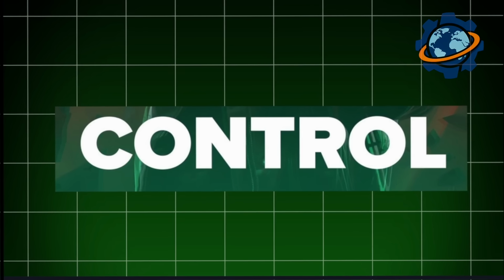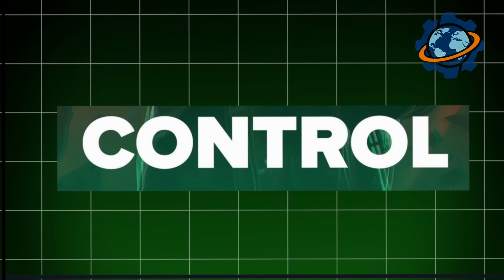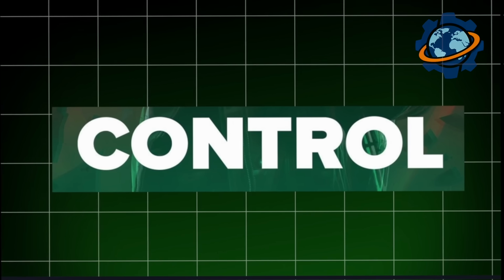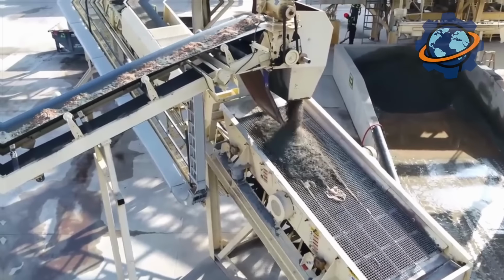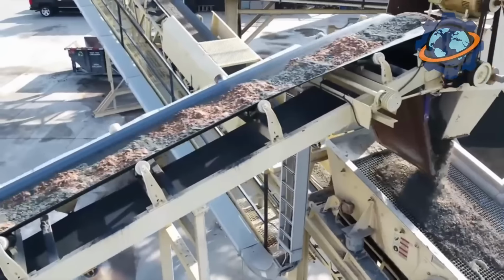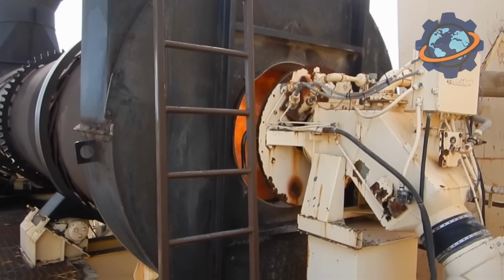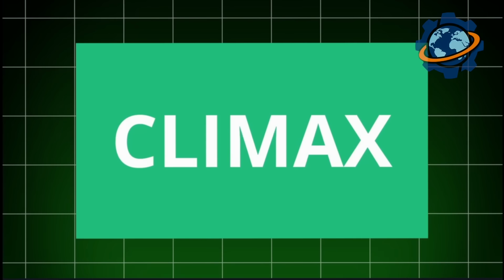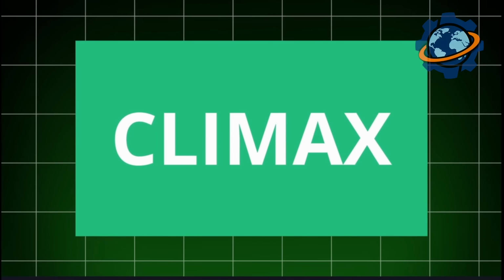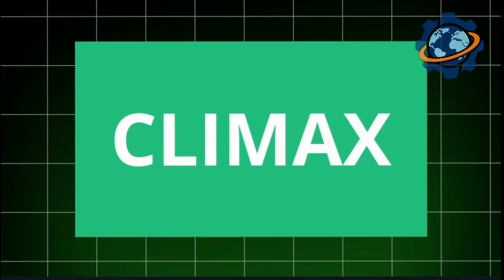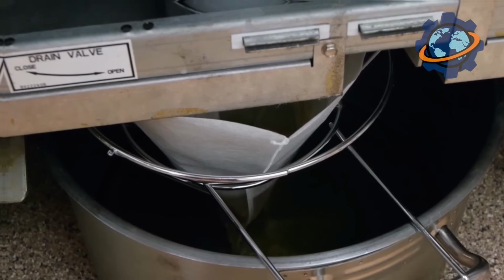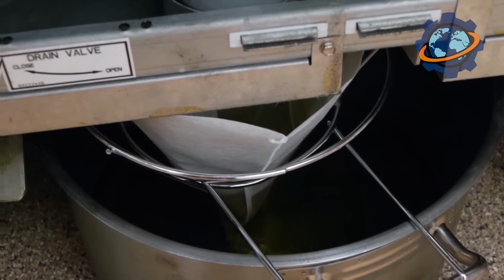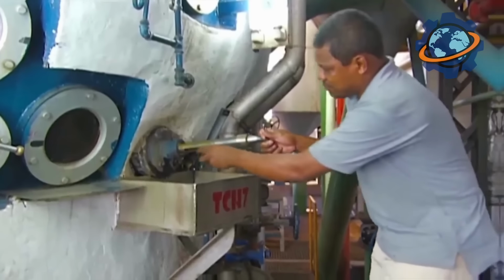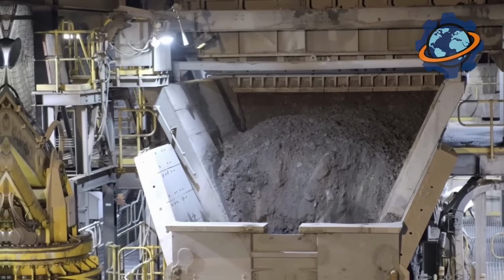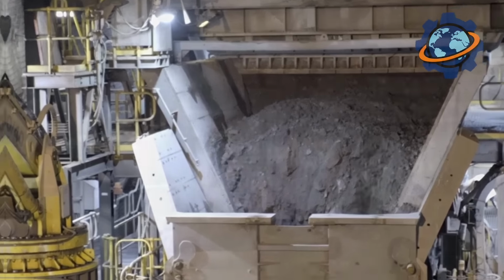There, it passes through another set of screens for a final quality check on the sorting, and then falls into hot storage bins. Meanwhile, in special insulated tanks, our black glue, the bitumen, is being heated up. It's also brought to a high temperature to make it fluid and runny. And now comes the climax. The computer gives another command. A weigh hopper, with incredible accuracy, measures out the required amount of hot stone of each size from the different bins. Then, a precisely measured amount of hot liquid bitumen is sprayed into this superheated stone mix.